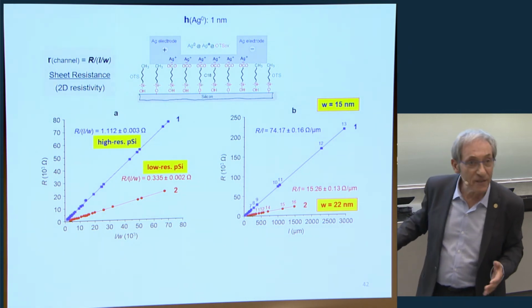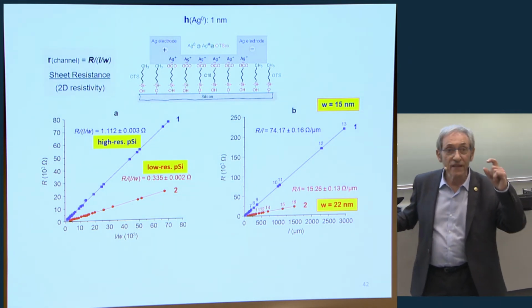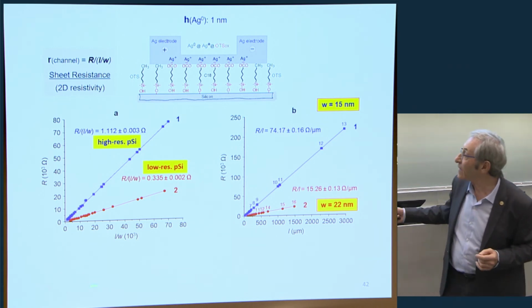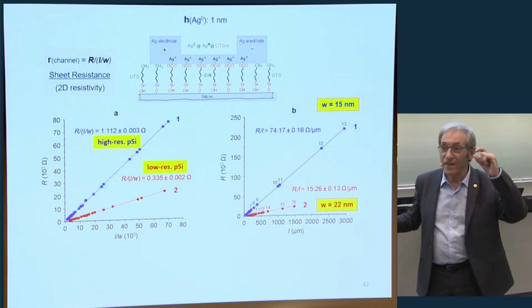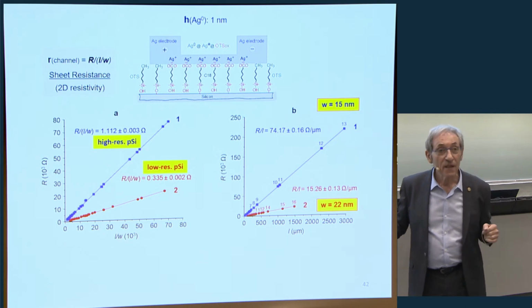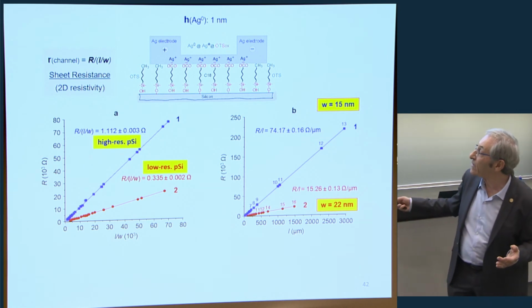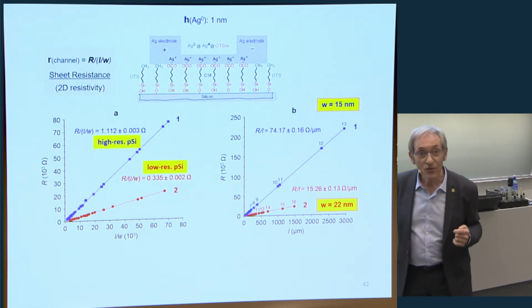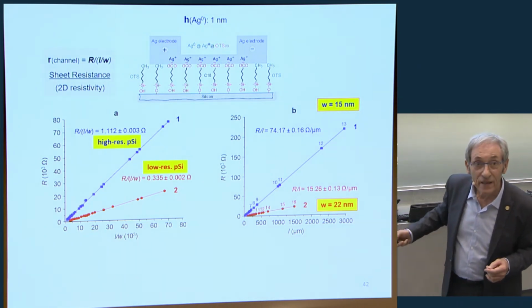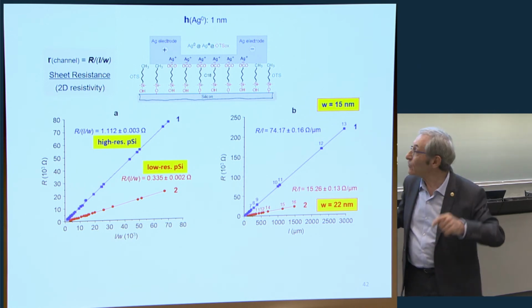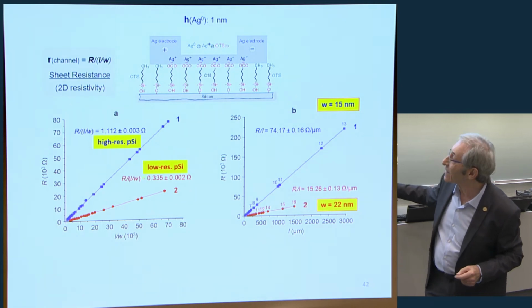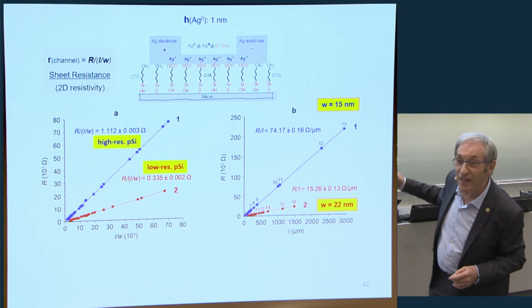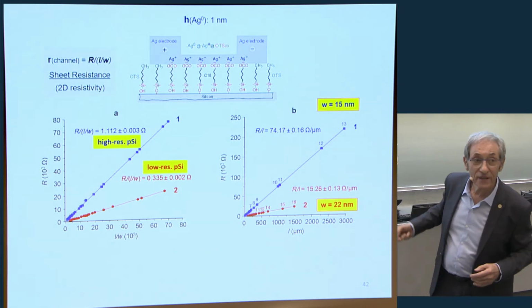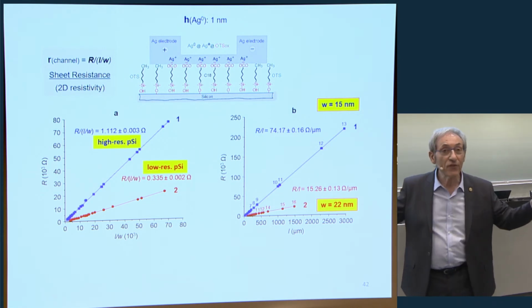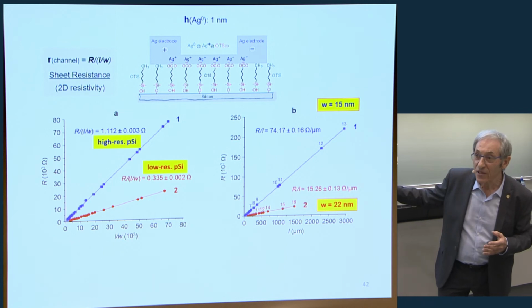But you see, these are perfect lines. So it means that the thickness must be the same along the line, because we divide by the length divided by the width, but the sheet resistance depends on the thickness as well. So these all must have the same thickness. Then, furthermore, we said, let's see what happens if we pattern only as a function of the length. If we pattern only as a function of the length and take all those dots that are on the line, it turns out that all of them have the same width by AFM, which in this case, on the low doped and high resistivity P silicon is about 15 nanometers according to AFM, and the other one is about 20 nanometers. So all these must be uniform. But if you look at AFM, they don't look so uniform. So the electrical measurements show us much more than the AFM shows.